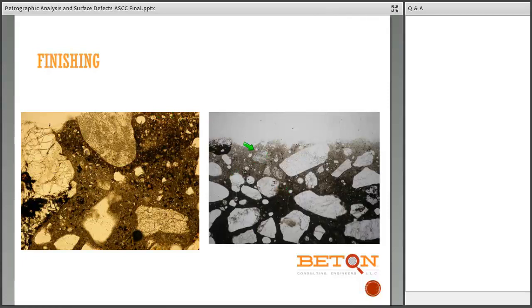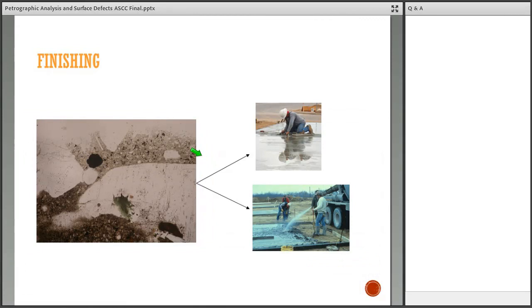Here, the opposite. This is the surface, and the surface has been exposed to water. Higher water to cement ratio at the surface, not so much at the bottom. So you can use petrography to see whether you have finishing problems. We have people finishing either the naturally occurring bleed water or this gentleman who read the specification that said do not add water to the truck after batching, and he understood that both of these will result in this condition: high water content at the surface or water cement ratio, lower water to cement ratio further down.